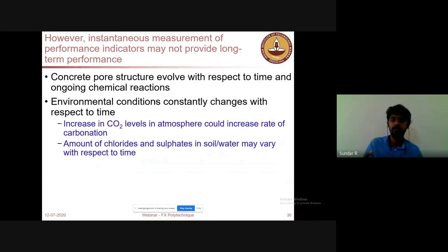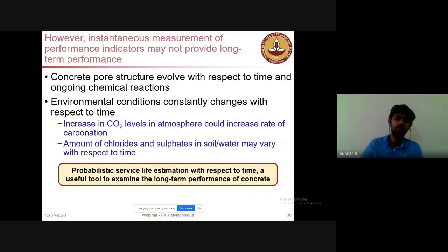So the measurement at one moment may not be sufficient to predict the long-term performance. That is why we have to go for a probabilistic service life estimation. So what is probabilistic service life estimation? This is a technique where the service life of the concrete is estimated by considering the variability in the input data also. That is why we are going to use probabilistic service life estimation as an important tool for generating design-based durability guidelines.